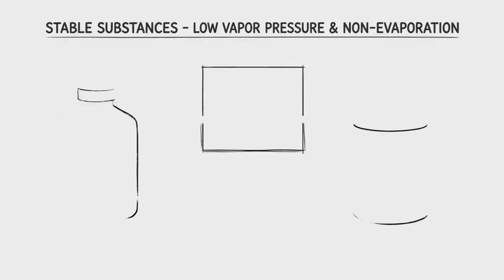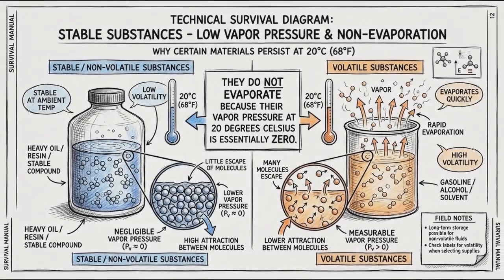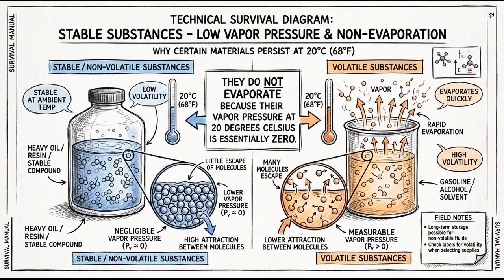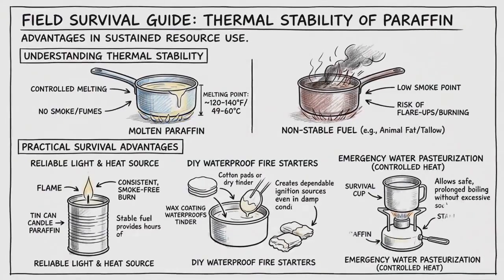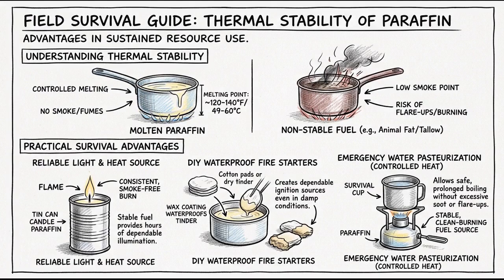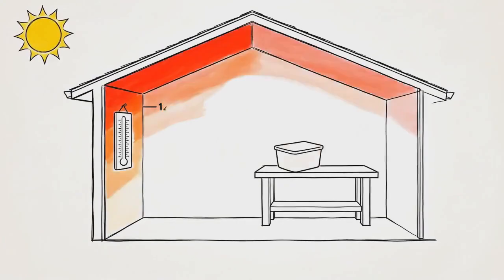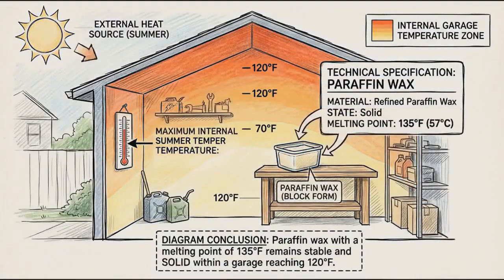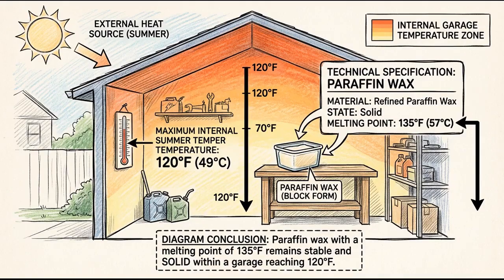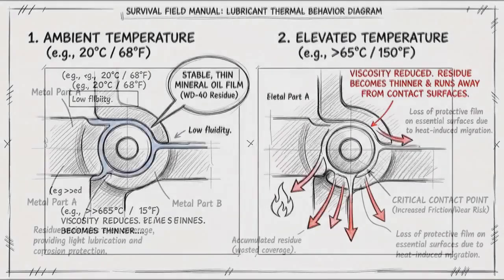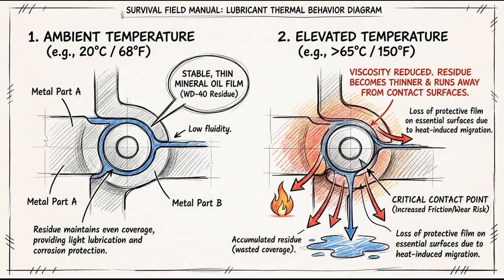The thermal stability of paraffin adds another advantage. In a garage that reaches 120 degrees Fahrenheit in summer, paraffin with a melting point of 135 degrees Fahrenheit remains solid. WD-40's mineral oil residue, already thin, becomes thinner and runs away from the contact surfaces at elevated temperatures. By autumn, the WD-40 treated hinge is dry and squeaking again. The paraffin treated hinge is unchanged.